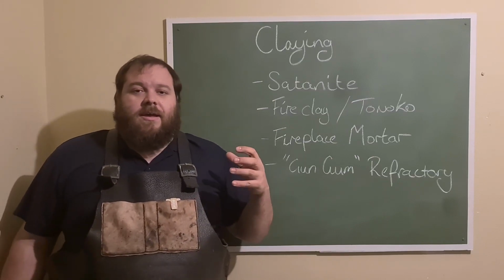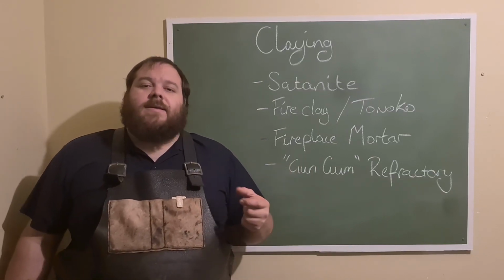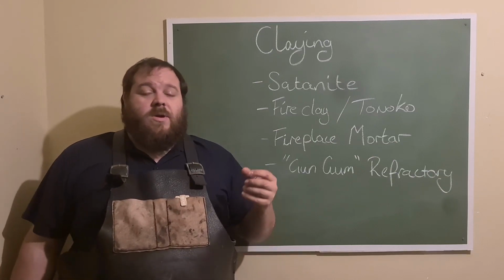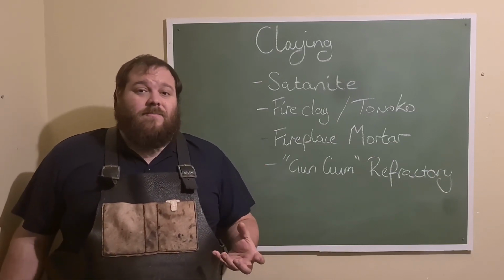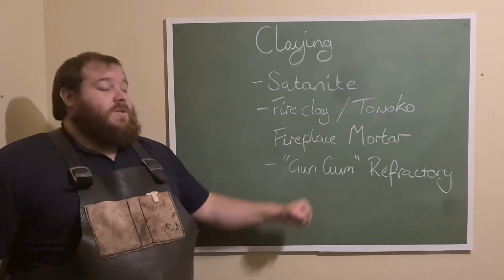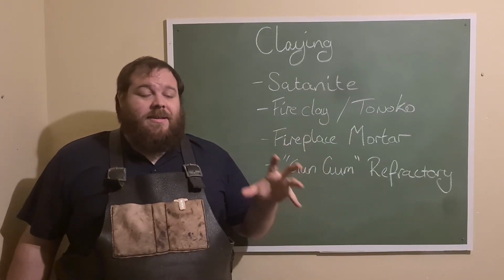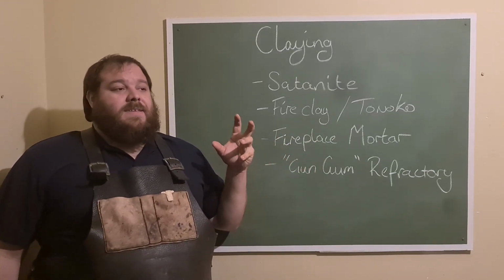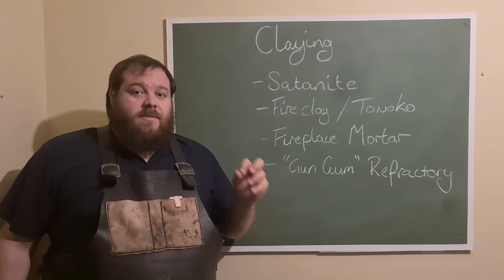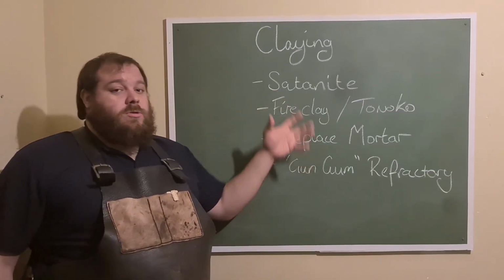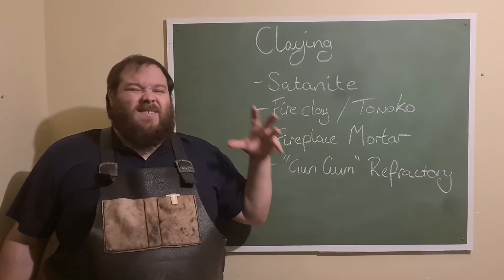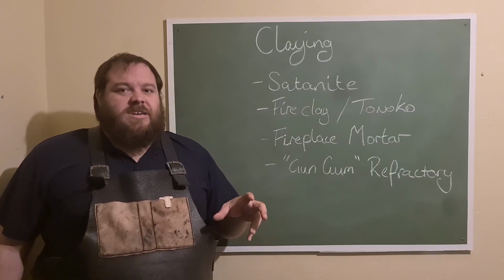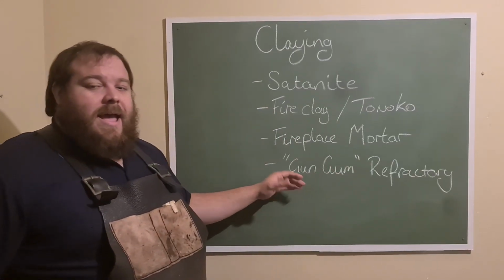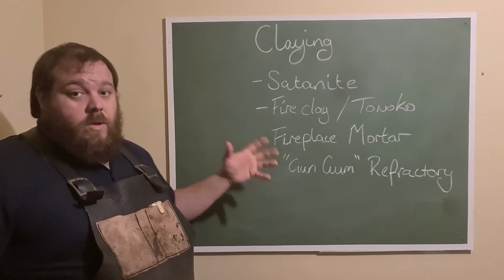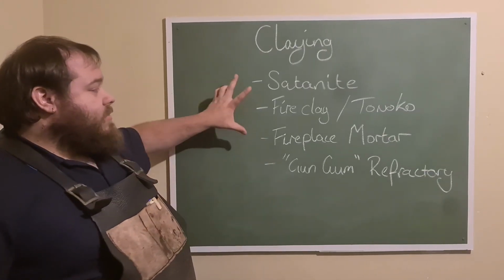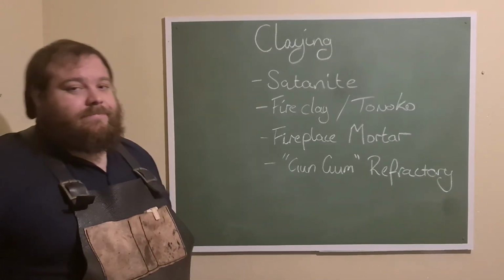It's not easily laid onto the blade, and it tends to lay on very thick, because remember, we don't really want a very thick layer of stuff. This stuff also tends to swell up when heated, and I think that's by design, because I think it's an insulatory refractory rather than actually a refractory mortar or cement. And so therefore it's not ideal, and so I wouldn't suggest it, but it will work. Any kind of refractory material will work, but the 3 top ones are those.